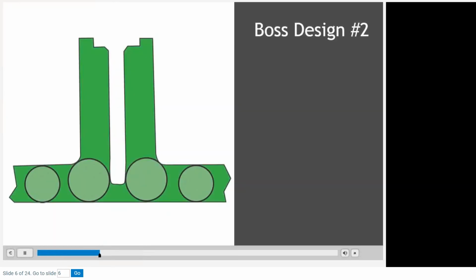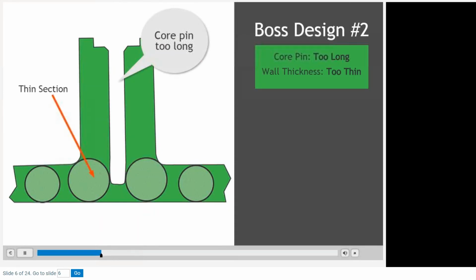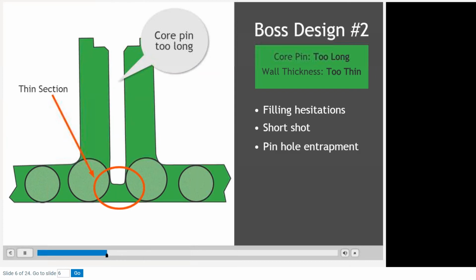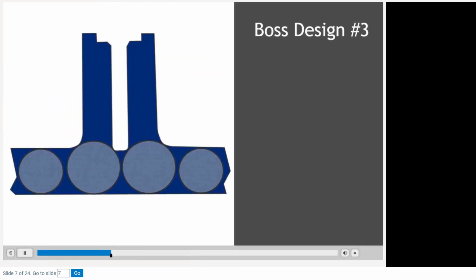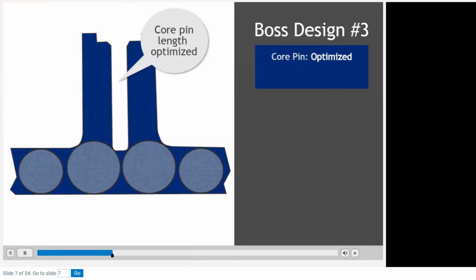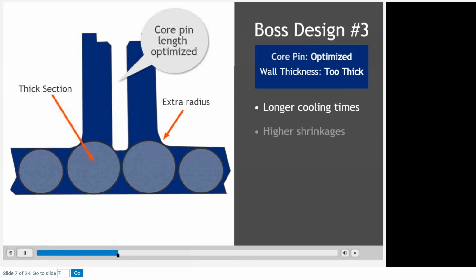Here is a boss design with a core pin that is too long, creating a thin section. In this case, filling hesitations may occur while the thin section fills, which could result in a short shot or pinhole entrapment. More information on this topic is available in Lesson 9, Gussets. Another boss design option shows that the core pin length was optimized, and in addition, a generous radius was added. As in the first example, this would create a thicker section that could lead to longer cooling times, higher shrinkages, sink marks, and possible voids.